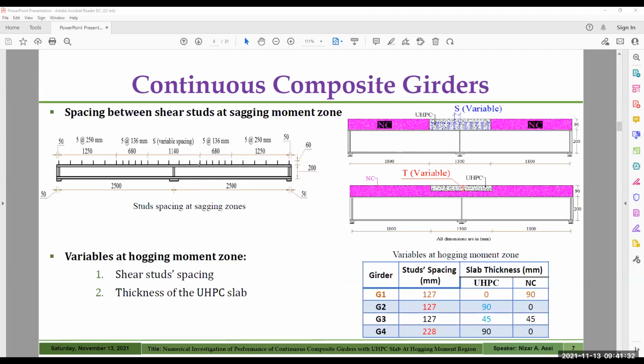The experimental work conducted previously considered only two variables: the spacing between the shear connectors at the negative moment region, which means the degree of shear connection between the concrete slab and the steel beam, and the thickness of the UHPC slab used at the hogging moment region. So four girders were cast and tested experimentally to consider these two variables. But that experimental work did not consider the effect of the length of this UHPC slab at the hogging moment zone.